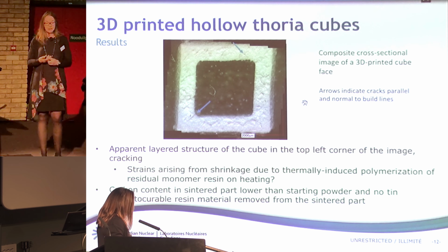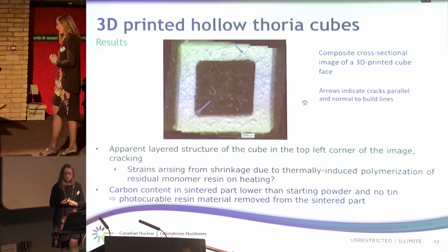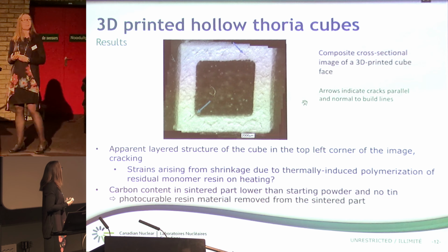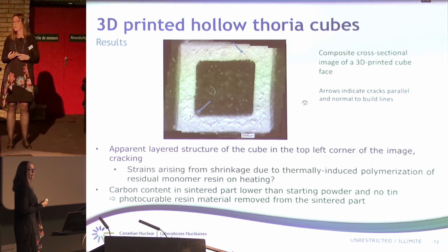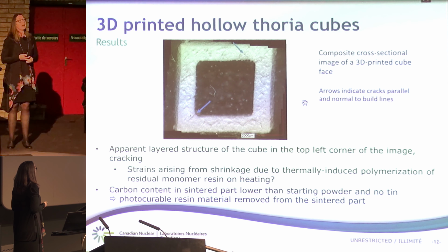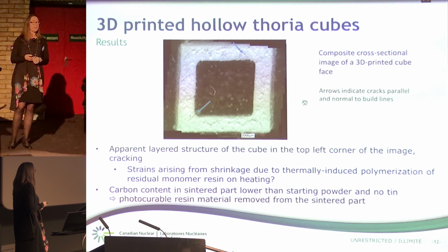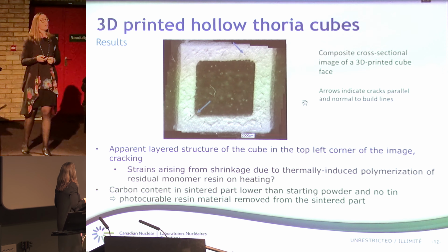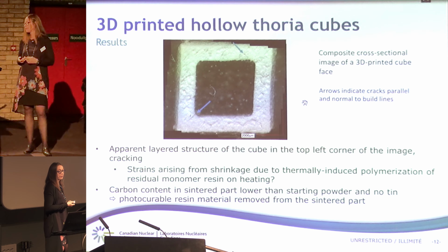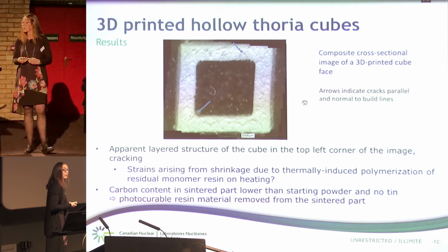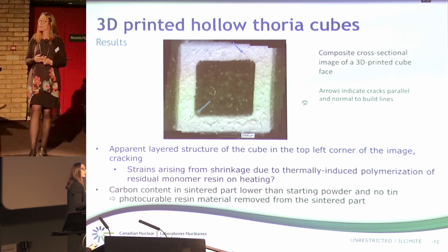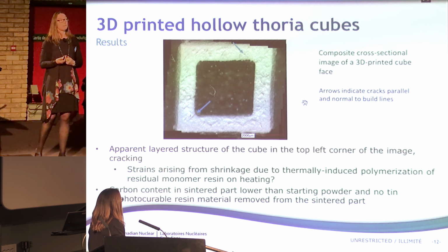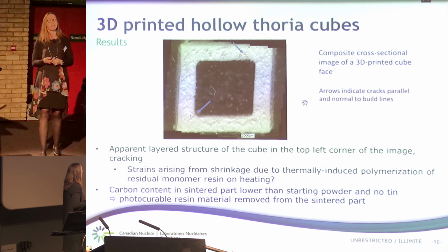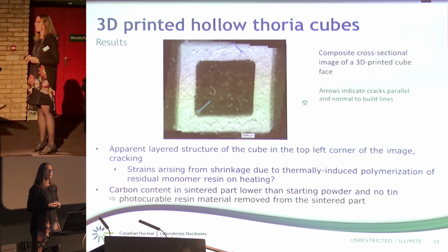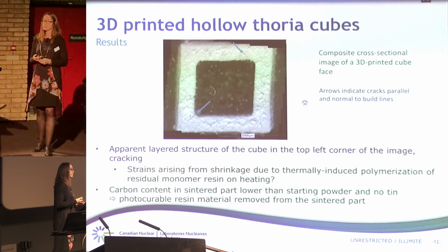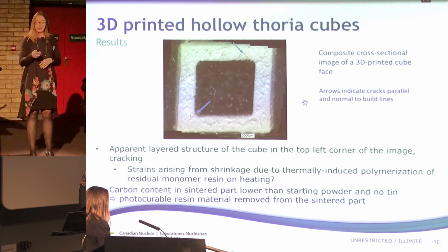And finally, we did some chemical analysis of the final part after sintering, and compared those with the thoria powder impurity contents. We were pleased to demonstrate that the carbon content in the sintered part was lower than the starting powder, and no tin was found in the final part. So we are pretty comfortable saying that all the photocurable resin material was removed from the sintered part. So there is no impurity due to this process.